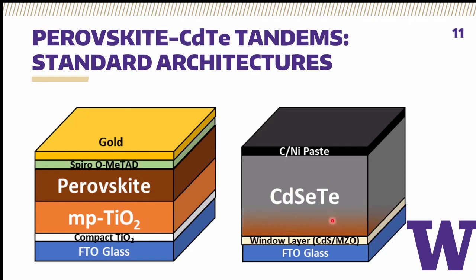And then the CdTe device is a more simple traditional P-N heterojunction with a CdTe P-type layer, a selenium backgrading that in optimal devices has a minimum band gap of 1.42 near the junction, and then a window layer, an N-type contact layer that has traditionally been cadmium sulfide, but in recent years has been moving more towards, I think, magnesium zinc oxide to create wider band gap window layer contact materials so that more light can get through to the CdTe device.